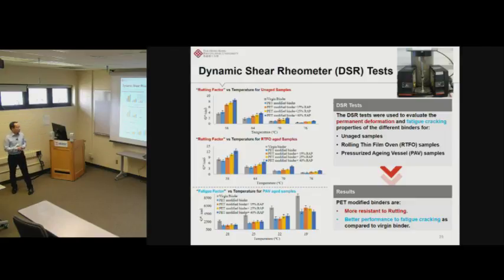So here we can clearly see the difference. Compared with the virgin binder, which is the first one, the PET modified binders, no matter how much RAP binder we have added, their fatigue factor is much lower. So this means we expect much better fatigue performance of the PET modified binders, no matter with or without RAP binder.